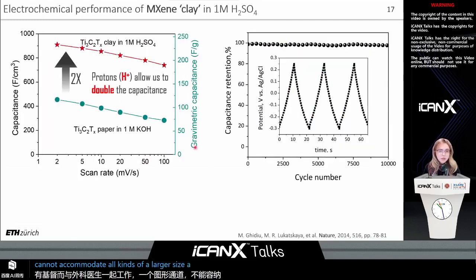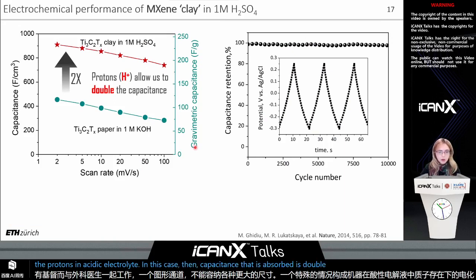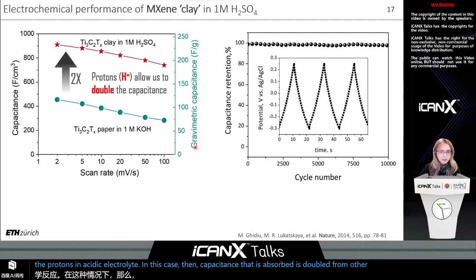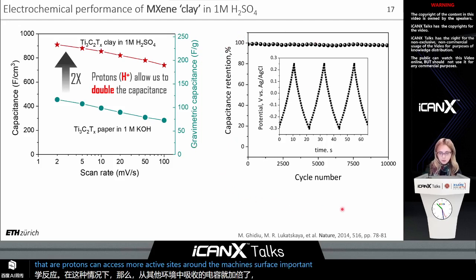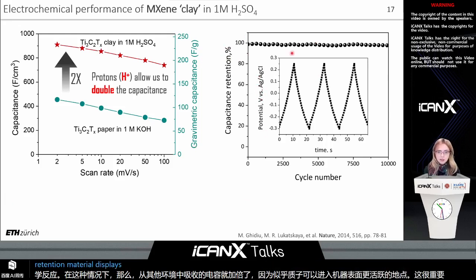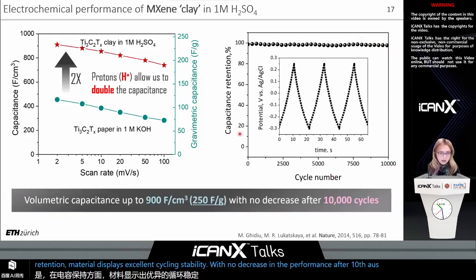A special case constitutes electrochemical response of the MXenes in the presence of the protons, so in acidic electrolytes. In this case, the capacitance that is observed is doubled from all other environments, because it seems that protons can access more active sites on the MXene surface. Important to mention that in terms of capacitance retention, the material displays excellent cycling stability with no decrease in the performance after 10,000 cycles.